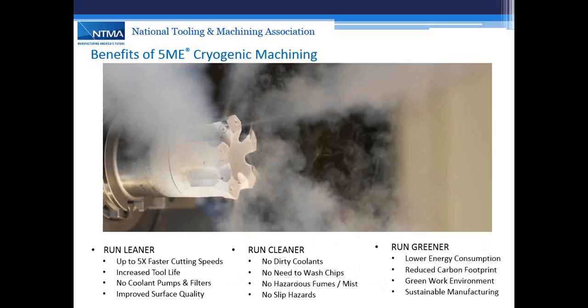Okay, so again, the benefits of cryogenic machining: you're running up to 5 times faster in some materials like compacted graphite iron with equivalent tool life. You increase tool life. In some cases, we've had finished turning in titanium where we've had up to a 35 to 50% tool life increase with double speed. No coolants, pumps, filters, improved surface integrity. From a cleaner perspective, there's no dirty coolants. The chips are dry. They don't stick to the sides of the machines anymore. Slip hazards on large machine tools are eliminated. If the operator needs to walk onto a large fixture to tighten up a large workpiece, no need to wash chips. So all those contaminants are basically removed from the system.